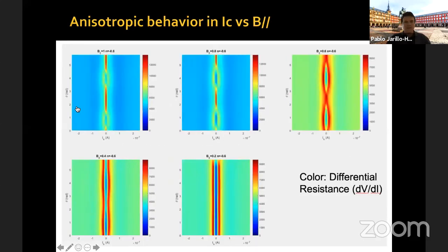Let me, in the next slide, just take a snapshot, which I've taken for a density in some units of 0.6. What you can see here, let's focus on this panel, is that there's some direction as a function of angle where the system is superconducting. Superconducting means blue. The system is superconducting for some angles, whereas for others, the system is actually insulating. It's not only not superconducting, but actually has a peak in the differential resistivity, which is what I'm showing here. So as a function of angle, the system has either finite critical current or zero critical current, and in fact, goes into the normal state.